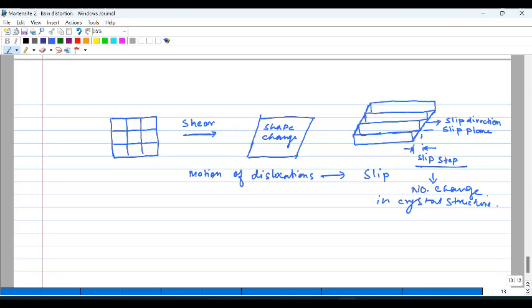Okay, so in case of Martensite transformation, we have a deformation which could change the crystal structure, and it has been found that that particular strain which is causing this change from austenite to martensite, leading to a change in the crystal structure, is a combination of a volume change, that is a dilatation along a particular direction, and a shear.